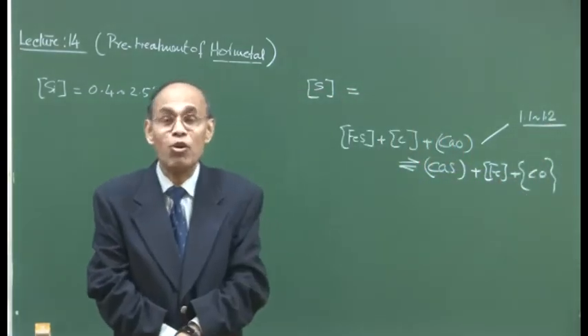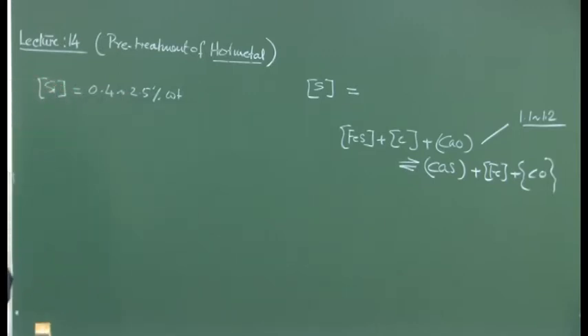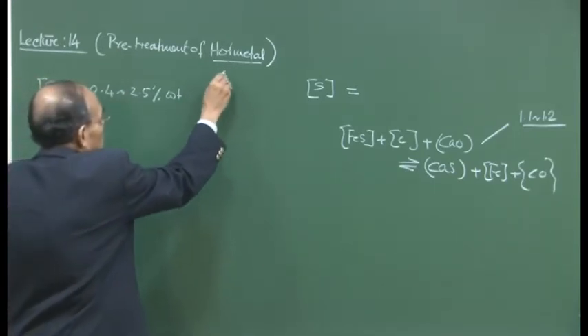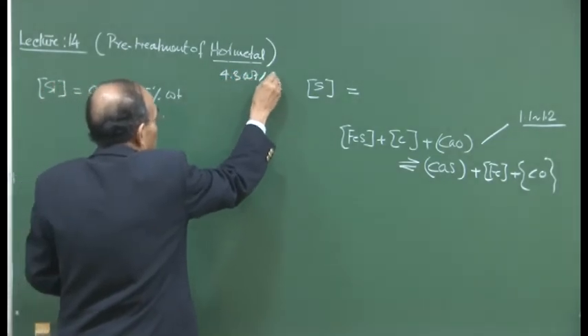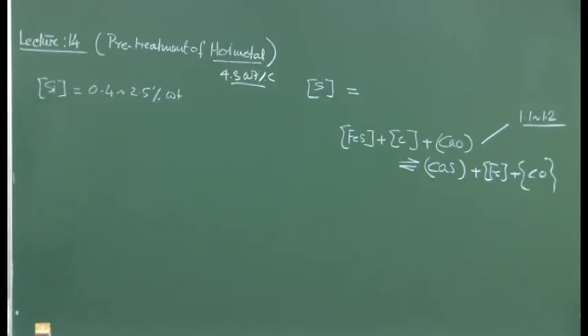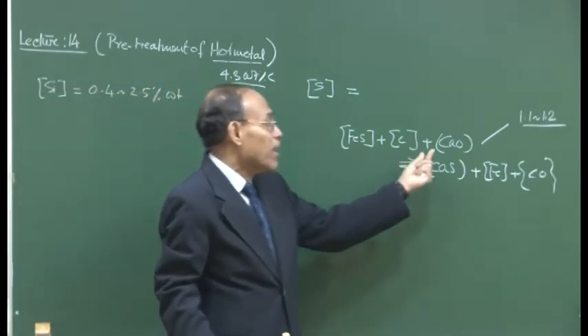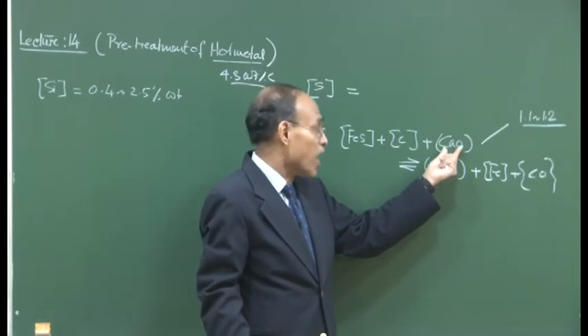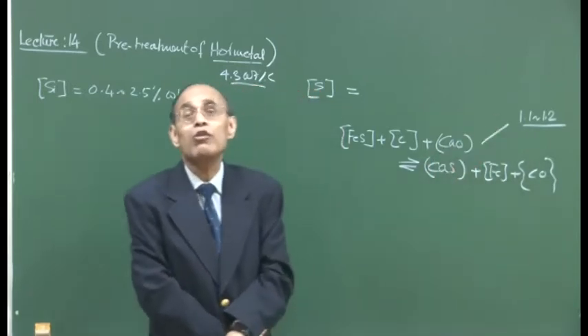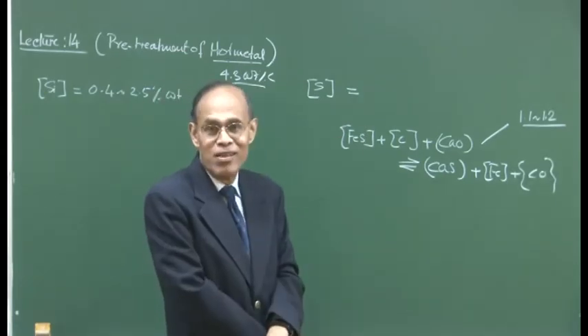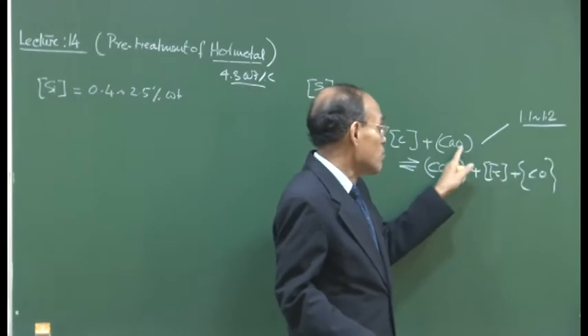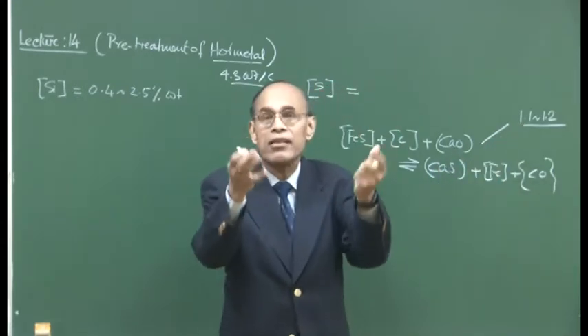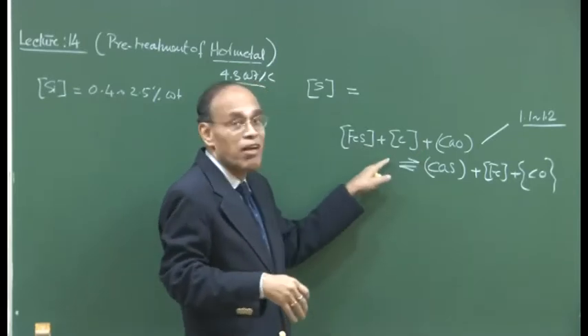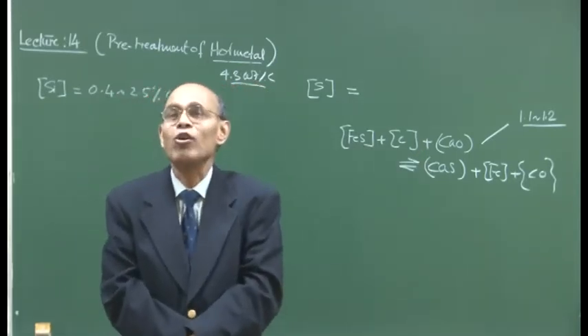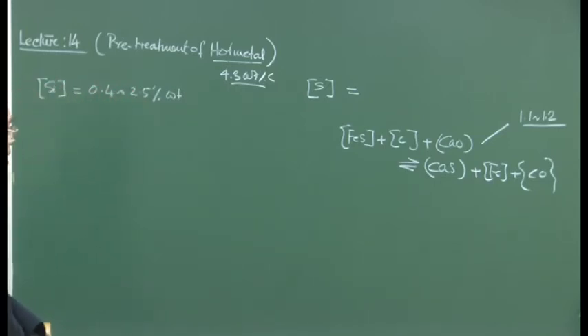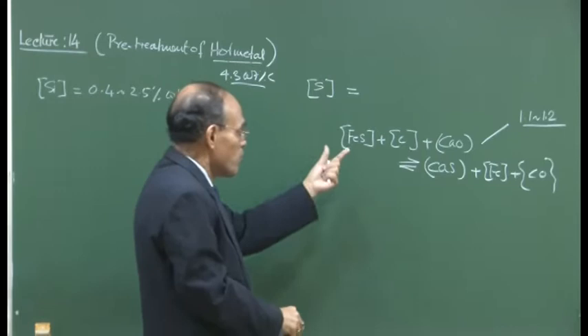On the other hand, in steel making, because we have excess temperature from carbon oxidation and silicon oxidation, so much silicon and so much carbon will produce enormous heat, and that will make avenue for using a very large basic slag, a slag with large basicity, and the basicity will go somewhere around 3.5 to 4. But that is not possible in the blast furnace. If you want to produce a slag with a basicity of 2, you have to jack up the temperature, because you have to keep the slag fluid, because this is a slag metal reaction. So the fluidity of the slag is a very important parameter here. We will discuss that when we write the kinetic equations for the desulfurization process.